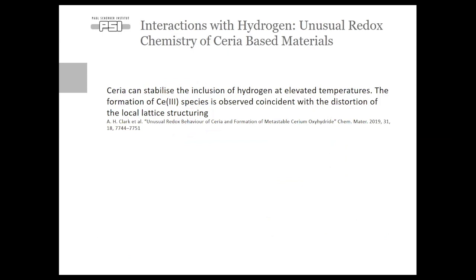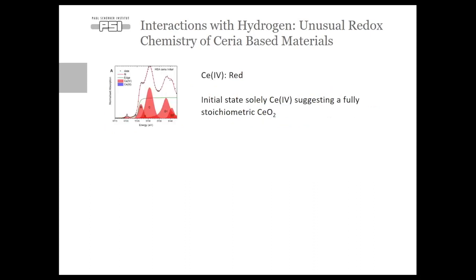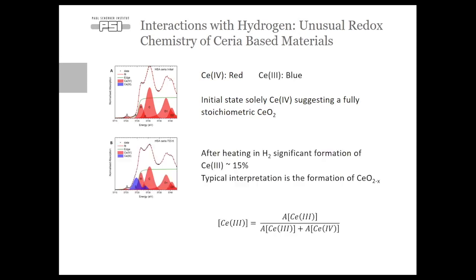So, why does this bring to my study? Well, one of the things which is still under some debate is, what is the interaction between ceria and hydrogen? And how does this form complex structures which can lead to significant catalytic benefit in, for instance, hydrogenation, hydrochlorination reactions? So, this is where XAS comes in. So, here I show you an example spectrum of a high-resolution XANES spectrum of ceria. Now, it has a very distinctive structure formed of multiple peaks. So, this is an example where we have a purely cerium-4-plus material suggesting a fully stoichiometric CeO2 structure. The experiment that I was conducting was to heat this sample in hydrogen and see how the structure changes. When you heat in hydrogen, there's a significant formation of a shoulder on the lower side of the edge. This shoulder has previously been prescribed to cerium-3-plus present in the structure, and typically is interpreted as the formation of defect structures. So, the loss of oxygen from the structure forming CeO2-X.